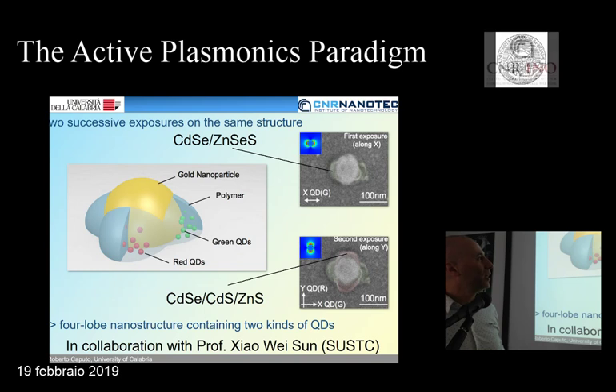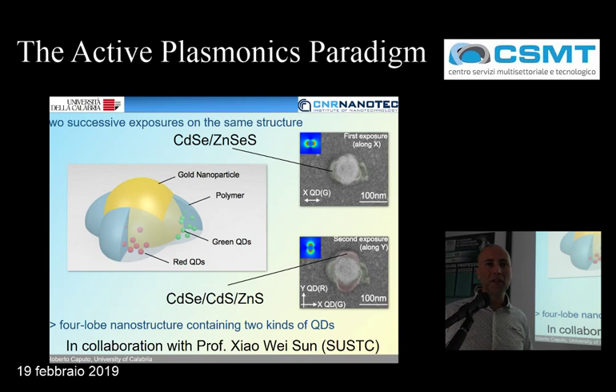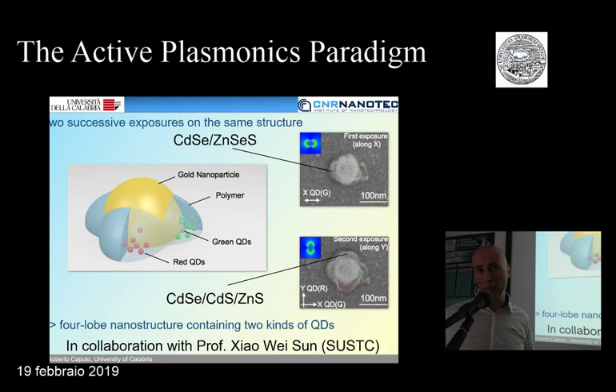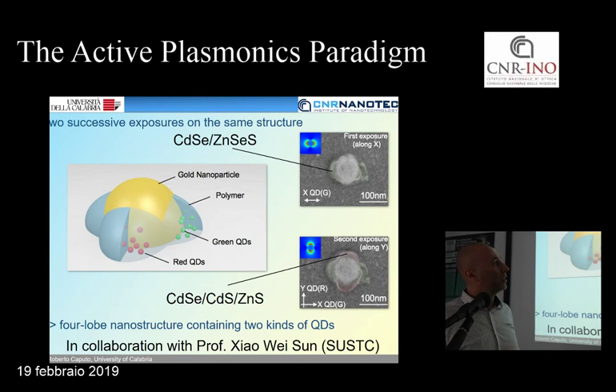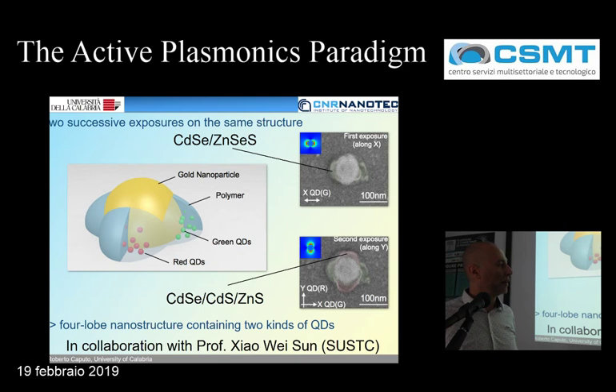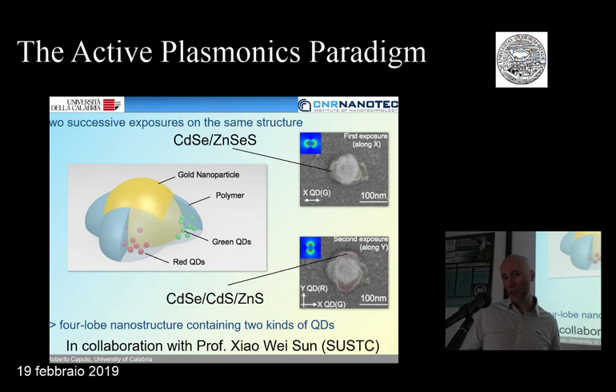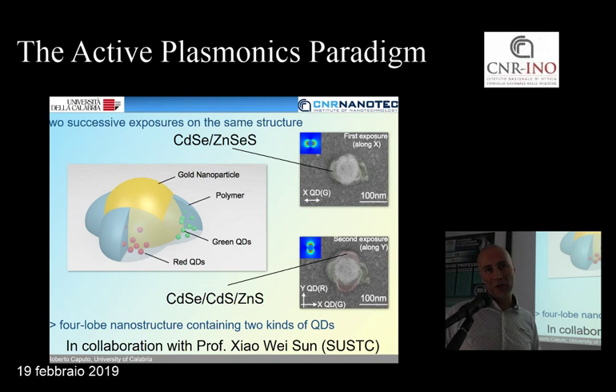The real experiment has been performed in a different way. We didn't want just to use a polymer to create this field replica, but a polymer doped with fluorophores, with quantum dots in particular, of different colors. And we made this procedure two times, first in one direction. The colors of the polymer are artificial, just to distinguish where it is. The first time has been made in this direction, the second time in this direction, on the same sample. And you get these polymer lobes of different colors, which can give rise to nanometric sources where you can control the emission wavelength.